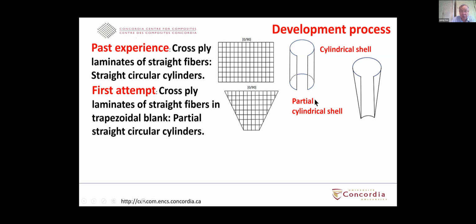But in reality, we did not get that. Basically, what you get is only what we call a partial cylindrical shell. So this is not a cone in the sense that the curvature at the top and the curvature at the bottom are the same. So this kind of layup sequence does not give a cone, but it gives you only a partial shell.